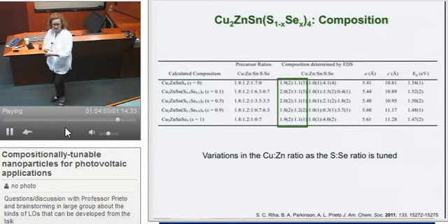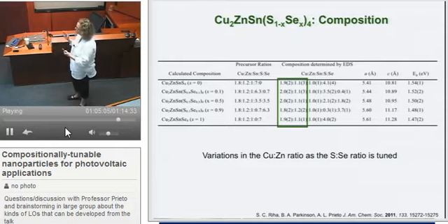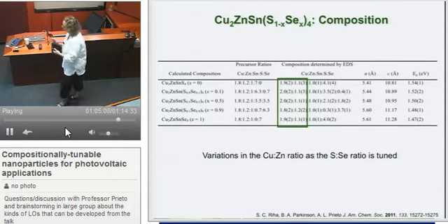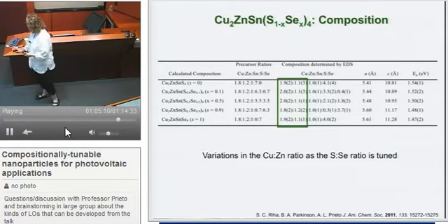We have tried ICP-MS to do elemental analysis, and our particles don't dissolve well. Various things precipitate out. So a more elegant elemental analysis we haven't figured out how to do yet. So this is done with a combination of EDS in the SEM, and XPS. Again, big error bars, but the trends show that we don't really have good control over that.